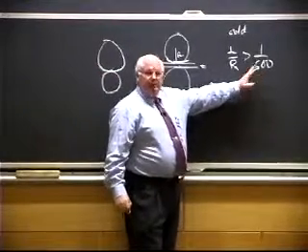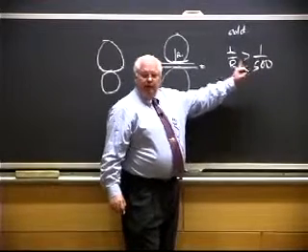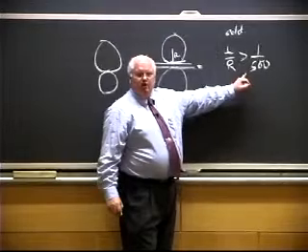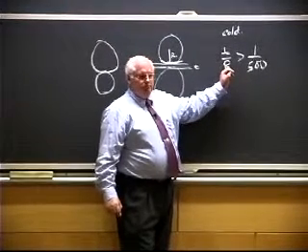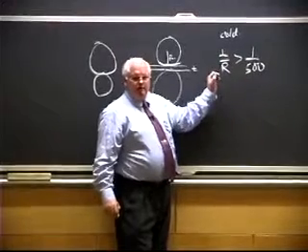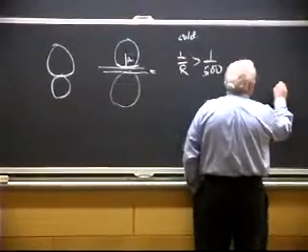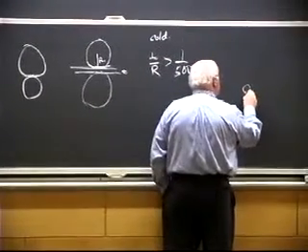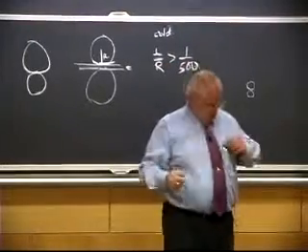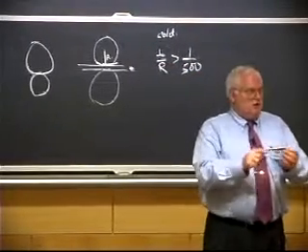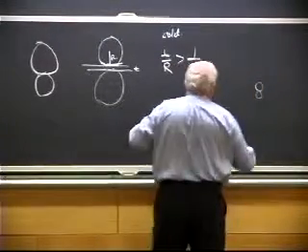So if I want to make, just think of this ratio now, if I want to make something that's 2 mil foil, the largest diameter roll I can have is 1 inch, right? 2/1000ths of an inch thick, then 2 over 1 inch is 1/500th. And that means that in order to roll very thin material, I have to have very small rolls. Well, the problem with very small rolls, if it's going to get very long, it gets nice and slender, and then the roll's going to bend. I lose all the stiffness in the roll, so I have to back it up.